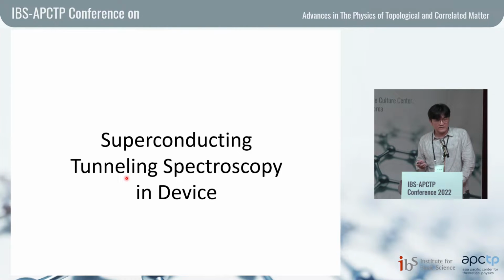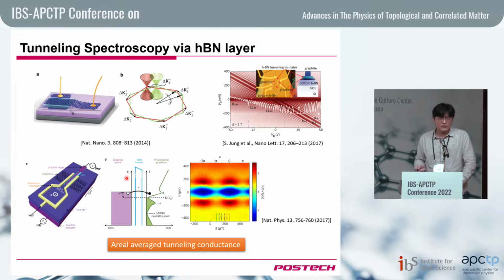So this is basically the STM, scanning tunneling microscope, technique. We're just mimicking the STM technique, but we cannot sweep the tunneling probe around the sample. We just put a tunneling contact to the material to locally see the density of states near this contact. There are many attempts to use tunneling spectroscopy to study 2D materials.